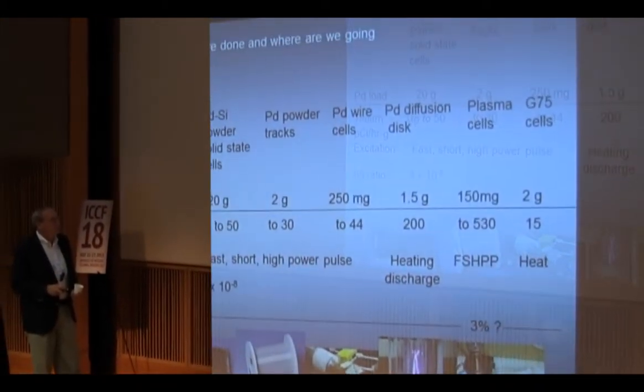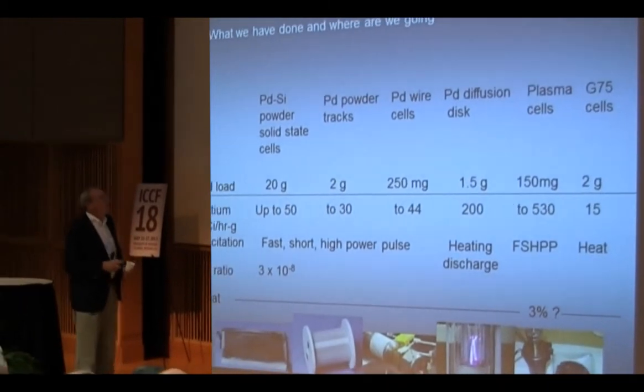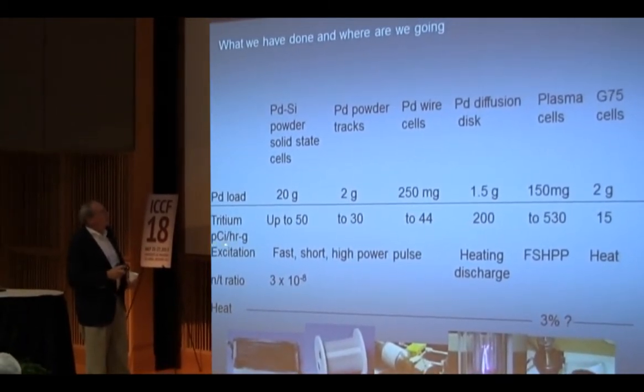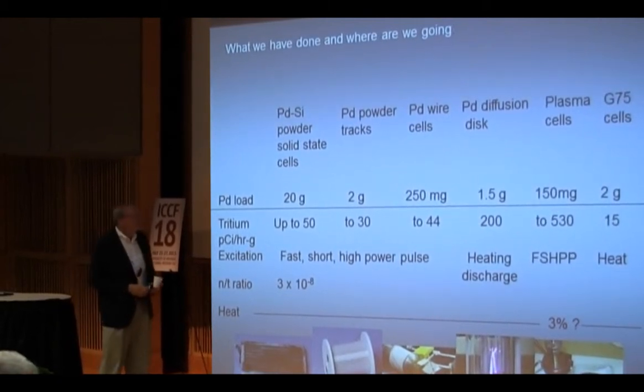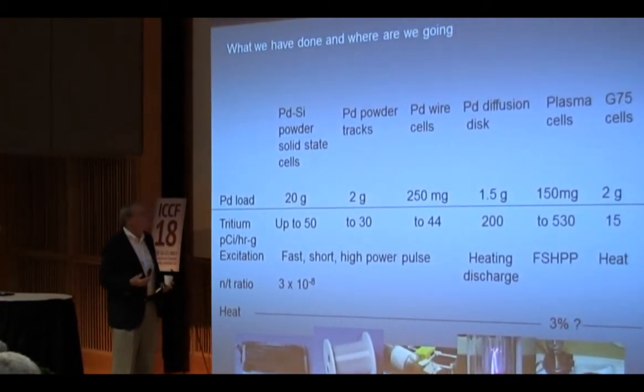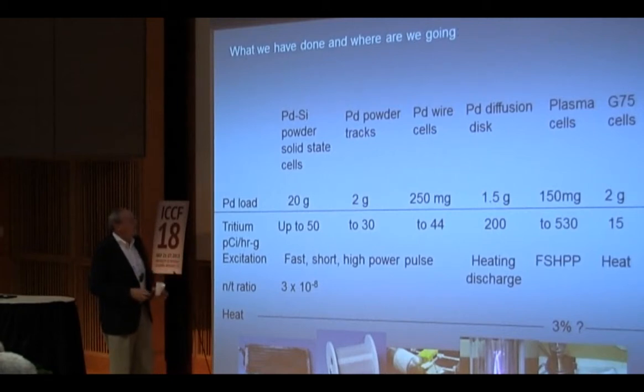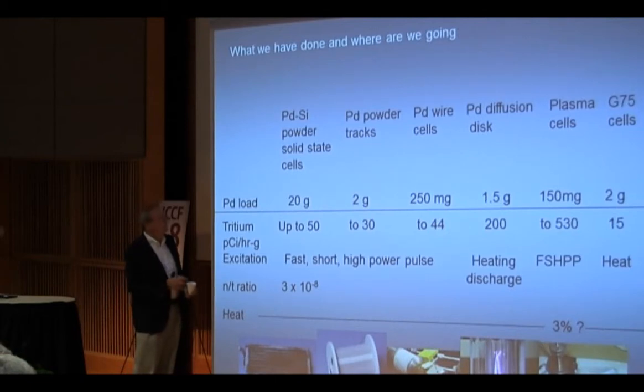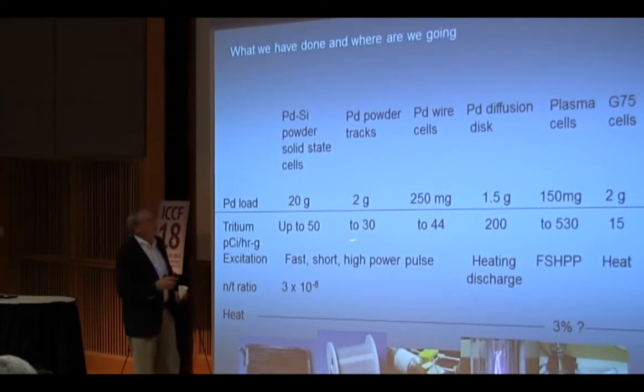And one thing I've never talked about was a casework, okay, where we looked for tritium out of the case experiment. So what we've done here is picocuries per hour per gram. That's kind of a figure of merit. You want that to be big if you want to see tritium or you want to see an effect. If you don't want tritium, you want excess heat. But what we want to do right now is compare all of these different systems. And the most efficient thing that we've seen is the plasma, okay? So we've had up to 530 picocuries per hour per gram out of those systems.